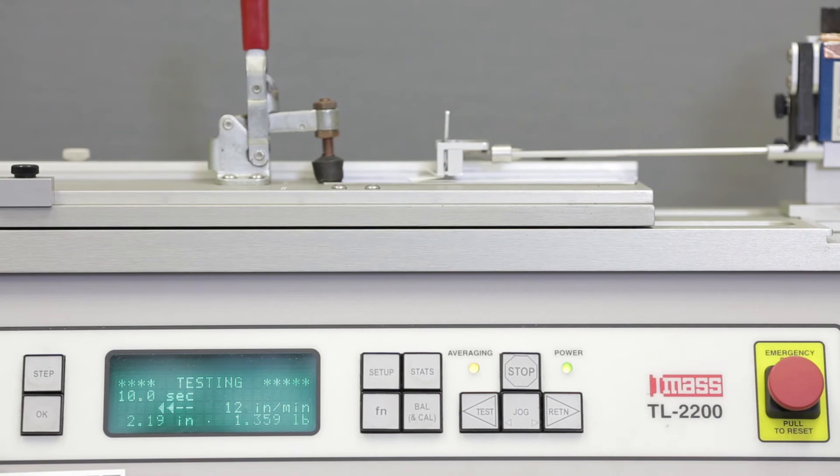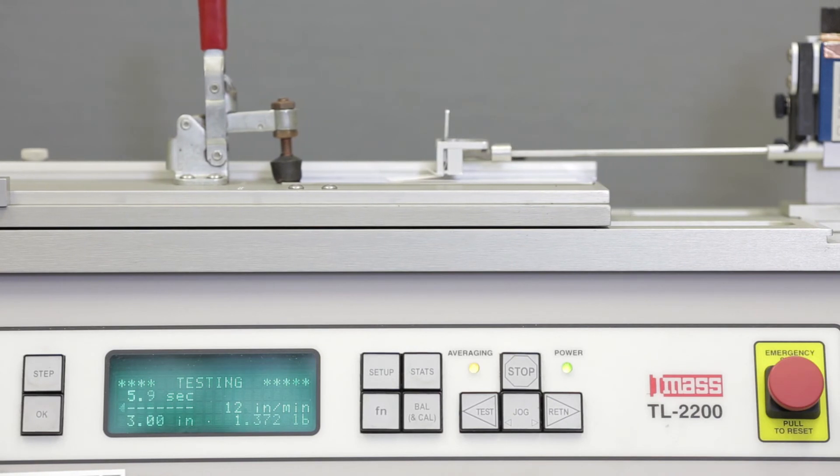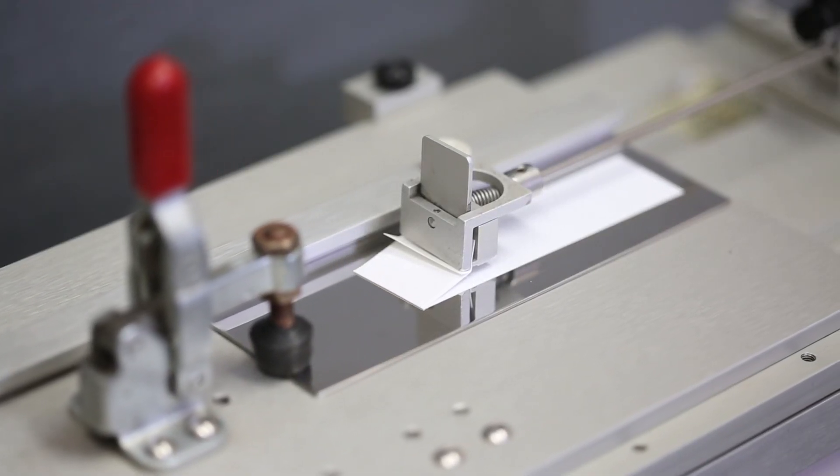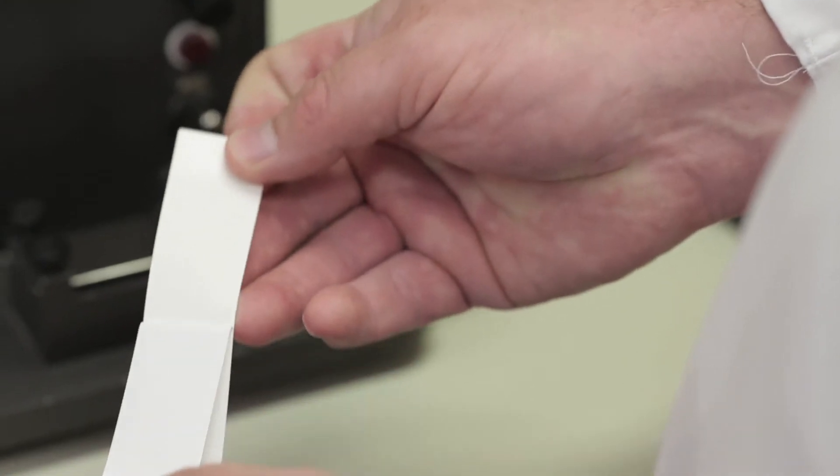At Franklin, we also test physical and performance properties of our adhesives, using standard 1 mil Mylar as the face stock and stainless steel test panels to benchmark adhesive properties. We also run peel, tack, and shear tests on specific face stock and liner to optimize the adhesives' performance.